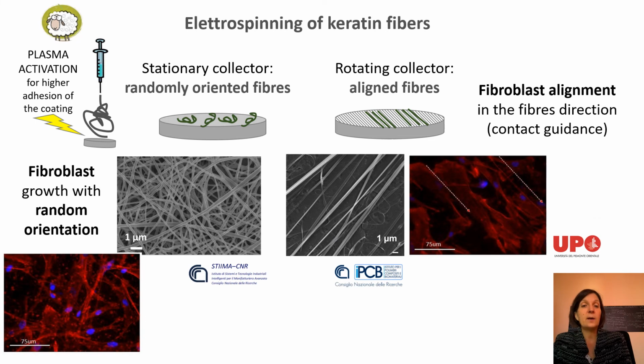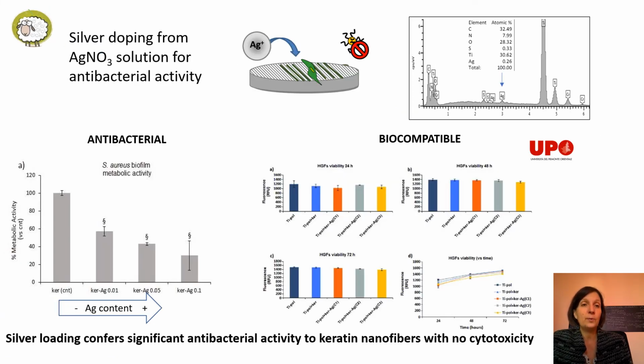And you can see here some random or some oriented nanofibers of keratin extracted from some waste in the industrial production of wool. And you can see here that you can have a random orientation if the fibers are random, or you can have an orientation of the fibroblasts on the oriented fibers. And if you dope the fibers with silver ions, you can see a pretty nice antibacterial action. And in any case, you have a biocompatible surface without any cytotoxicity.